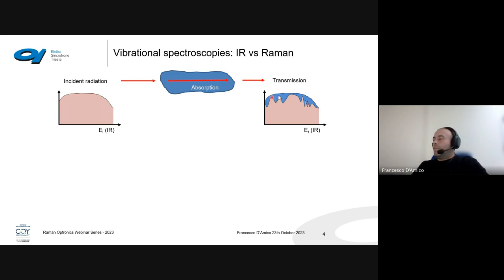attenuated by the amount of the blue part of this graph, and this blue part of this graph is substantially the vibrational infrared spectrum. Each peak corresponds to a specific normal mode as seen before, and therefore from the position of this peak and from the line shape of this peak, we can deduce a certain number of properties. This is the first way to detect information about vibrations.